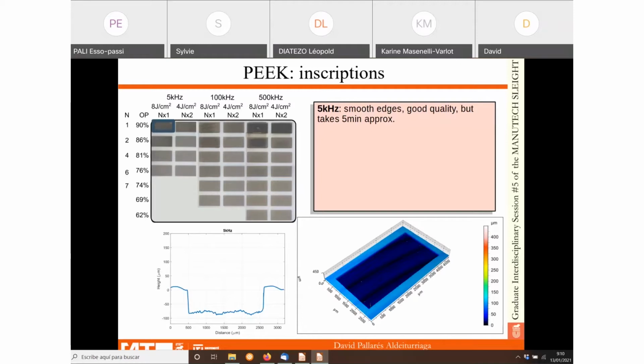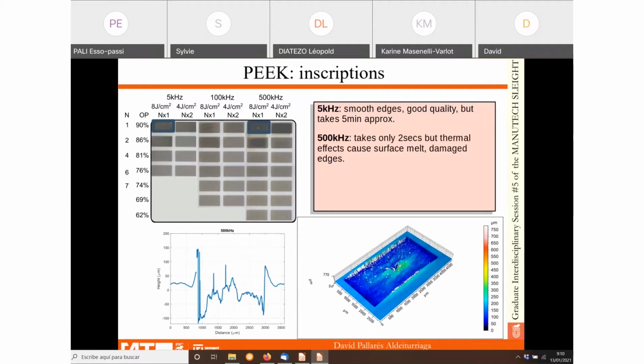Okay, what's the simplest thing to do? Well, we can just increase repetition rate. So in this case, bravo, now it takes only 2 seconds, but the confocal image reveals that there are a lot of thermal effects that have caused surface melt. The edges are damaged. There's also some material deposition on them. Also, the average depth has increased, given all this damage. So I think it's better to look for something in between or a way to avoid this damage.